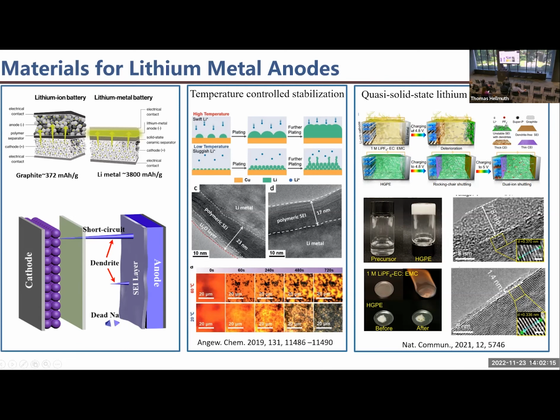Then we also use the polymer additive. So the polymer additive actually stabilizes the interface. The interface, once stabilized, can protect the metal from formation of individual species, islands, which can eventually grow into dendrite. So if we have a stable interface, that can prevent the dendrite formation, and then the battery can cycle very stably. And also the polymer can prevent the battery from catching fire. So it can not only increase cycling life, but also prevent battery fires. Anyways, so these are different ways, and there are other ways as well.